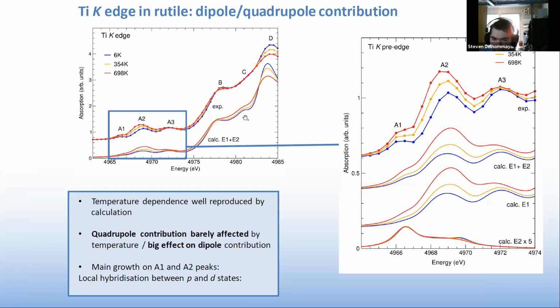performed. So here it's all the contributions at once, so dipole and quadrupole, E1 and E2. And here is just a zoom of the pre-edge region where I separated once again vertically all the contributions. So here we have the E2 contributions times 5 because else it's too small to see anything, and the dipole contribution and the sum of the two, which is meant to be compared to the experiment.